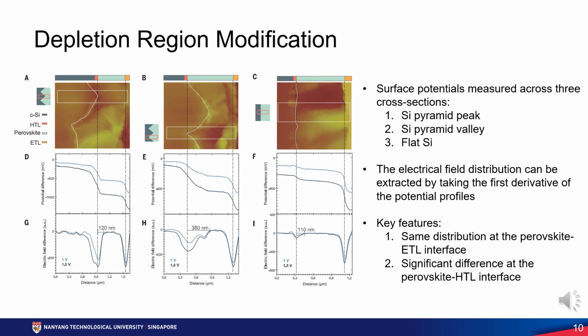In this work, the authors measured potentials across three cross-sections, for the textured tandem cells at the silicon pyramid peak and valley, and also for a flat silicon tandem solar cell. This gave the following potential profiles as shown in figures D, E, and F. By taking its derivative, the electric field distributions are extracted in figures G, H, and I. From this, we can see that the distribution is similar at the perovskite ETL interface, as it is identical for all three. But there is a significant difference at the perovskite HTL interface. The electric field extends far deeper near the pyramid valleys for the textured tandem cell.